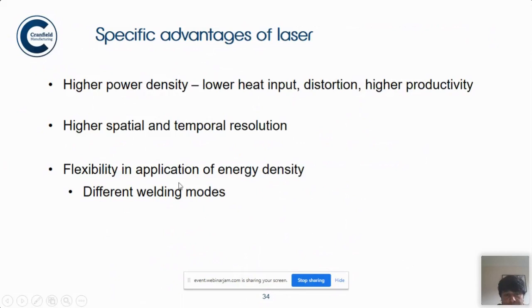It can create different welding modes. I'm sure you have heard about terms like keyhole welding and conduction welding, and all these can be done very flexibly using a laser. You have very high spatial and temporal resolution, which basically means where you apply the heat, you can control to a very high degree, and temporal resolution means for pulse laser, you can have very accurate pulse shapes. So the application of energy with respect to cycle time can be controlled very easily and very accurately. Higher power density generally gives you lower heat input, thereby lower distortion, higher productivity, and all this.